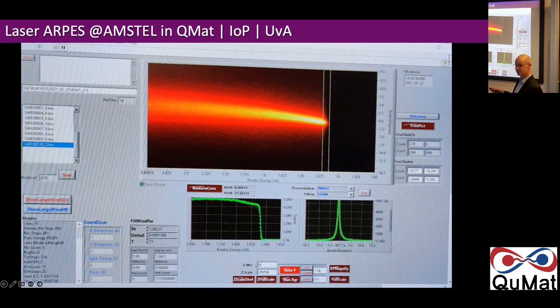This is simply the band. And because we're measuring, we can only measure the many-body version of this. We see that its width is changing as a function of its energy away from the Fermi energy, and that's related to its reduction in lifetime. You can see the kink here is changing its slope. If you very simply say it'd be linear with this slope, linear with that slope, you can get out the lambda for the electron formula.